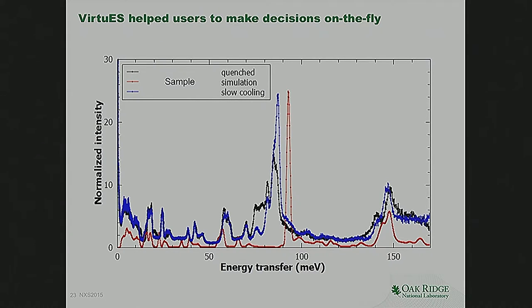Usually you cannot calculate very effectively the intensities of Raman or infrared, whereas in neutrons, we really can rely on the relative intensity. You see this peak in here, it's not precise, it's not perfect. But there's one peak here, there are two peaks here, one with the shoulder. This guy in here is just two peaks. And this peak in here with the shoulder, despite not being exactly precise and exact, the relative intensities, all of them, have to be preserved.